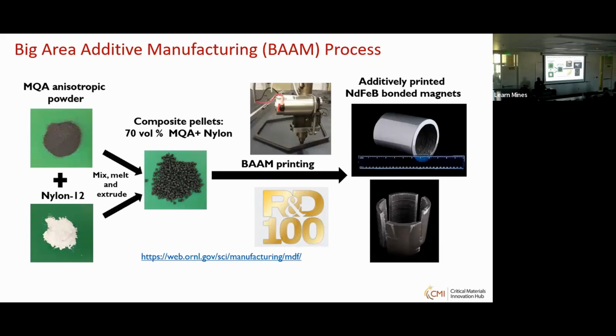Then with time, what we started doing is using big area additive manufacturing. This is fused deposition modeling. This is an example. You can take the magnet powders and mix with nylon powder. Instead of a filament, you have chopped small pellets of mixed magnet and nylon. Once you have a pellet, you can print with large deposition. In fact, Oak Ridge demonstrated large turbine blades, made in different sections. You can do an 80 meter long process. It's a huge process.